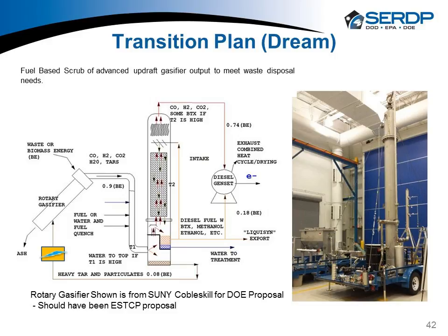The transition plan: I really think there's potential with the idea of using an updraft gasifier, like a rotary gasifier, to produce a high tar stream. If we quench it at the right temperature, we could ideally knock out the heavies, keep the temperature still pretty high so that a lot of the lighter hydrocarbons go up into a scrubber. The scrubber would run on the JP8, and again, we could run high temp in this T2 zone and push over a lot of the aromatic hydrocarbon and burn it in the engine, or we could take the liquid phase, do some filtering and purification of that, and run it into a diesel genset. We actually did make a system like this. We haven't fired it up yet, but we did want to propose that for follow-on ESTCP work.